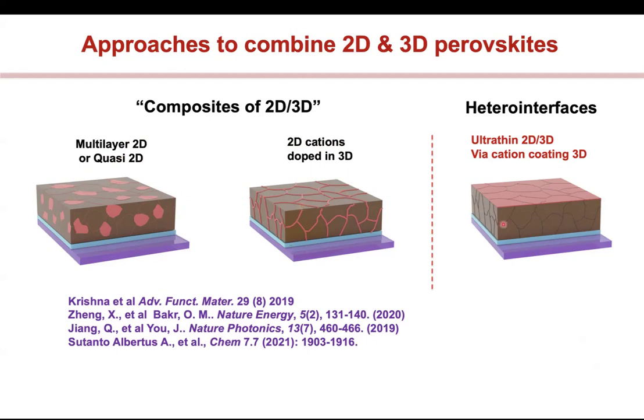And the third most popular approach has been taking one of these cations that you have, and you disperse them in a solvent which does not dissolve your 3D layer. So if I take this and spin coat it on top, for example, if I take butyl ammonium in isopropyl alcohol, which does not dissolve your 3D perovskite, then this cation can steal some of this lead iodide from your 3D and form a very thin layer of your 2D perovskite on top. Essentially, this is like a passivation layer that you get on the top of your 3D perovskite. Okay.